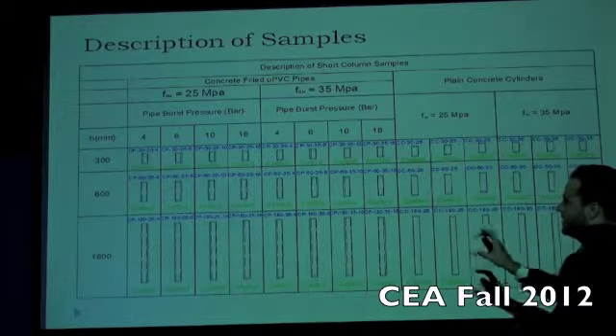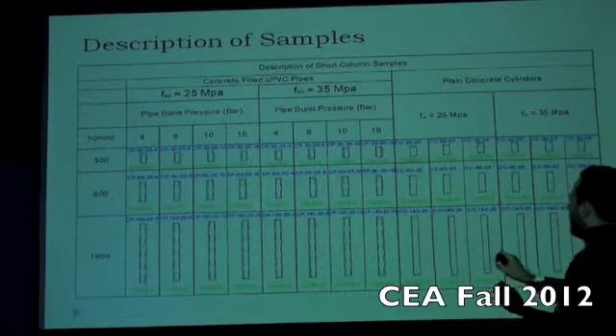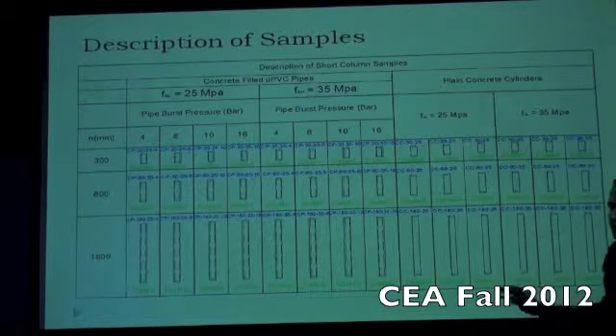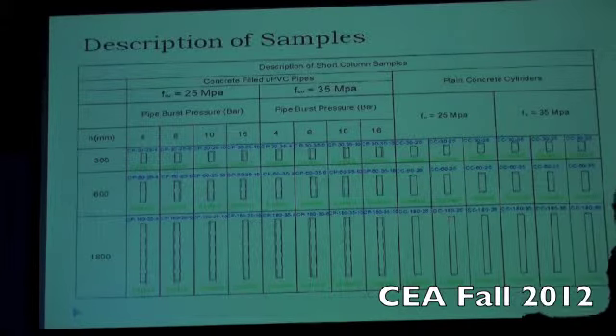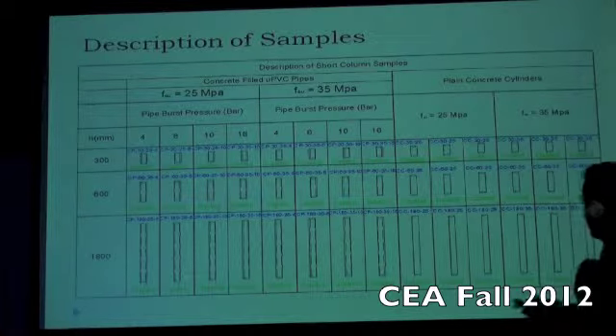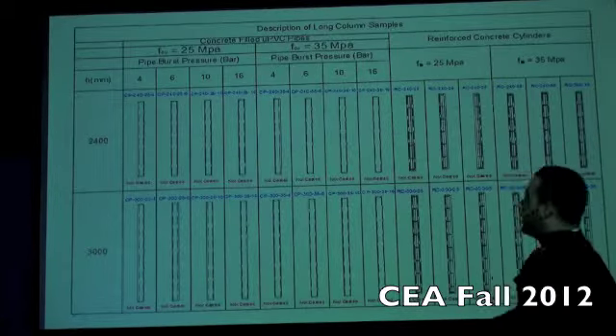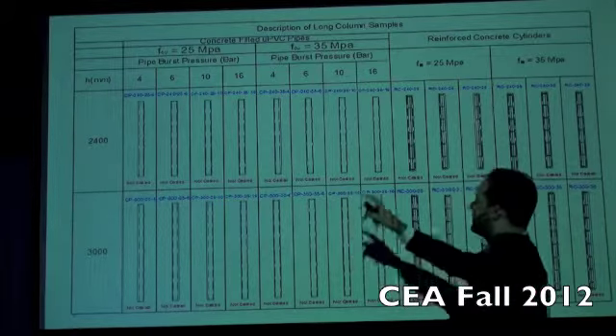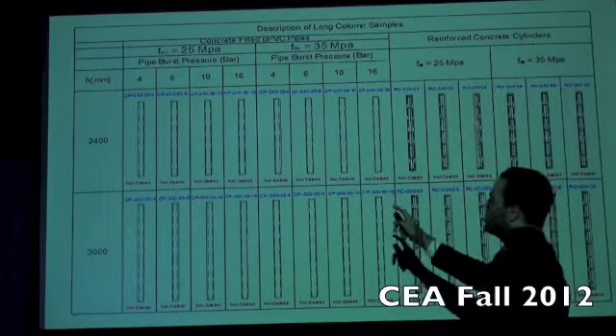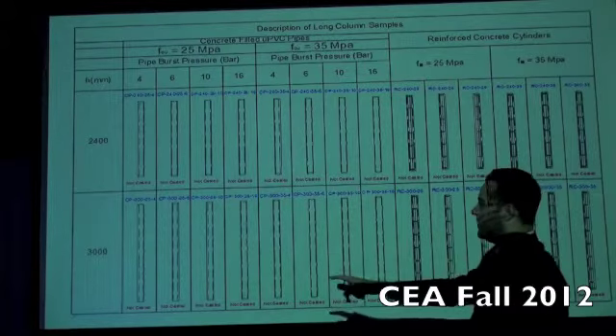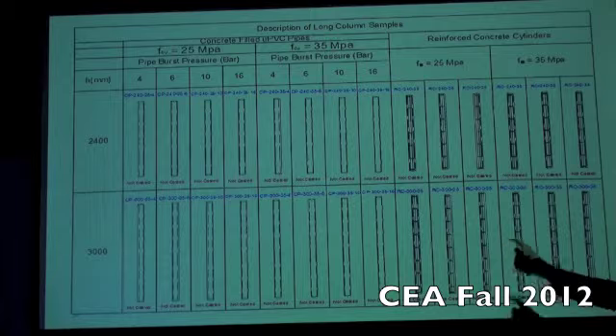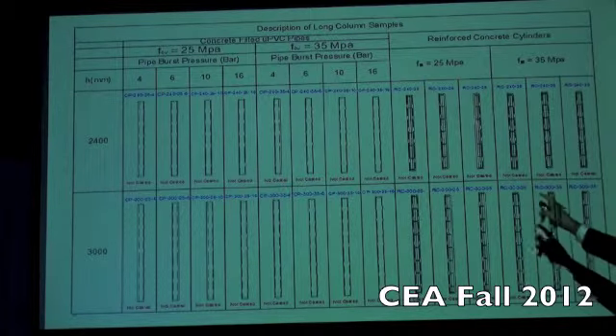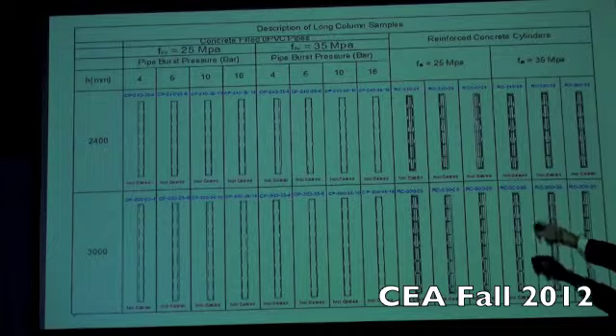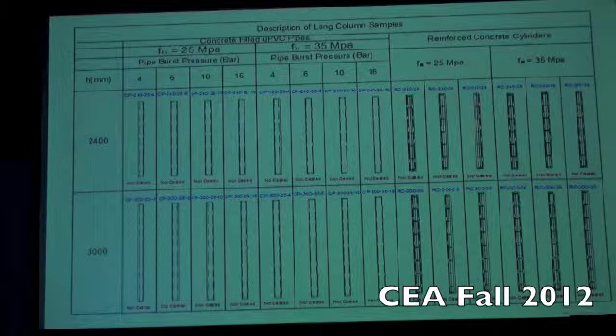All of these pipes have been cast, but we didn't yet do the samples of the long columns. We didn't yet cast them with concrete. Here are also the long columns, different concrete strength, different bars, with height 240 centimeter and 300 centimeter, sorry. And for the plain concrete, we use minimum reinforcement, just as I said before, to hold for testing, to decrease shrinkage and to avoid tension in concrete.